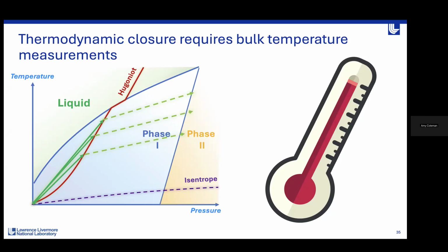We've got heating from work within the sample, heating from our ablation plasma at the front of the physics package, and if we're generating X-rays with a foil in the chamber, additional heating from those X-rays being generated. So when we give these isentropes coming from a measured shock state, we've typically been giving these as a lower bound on the temperature — in reality we'd expect the temperatures to be a little higher.